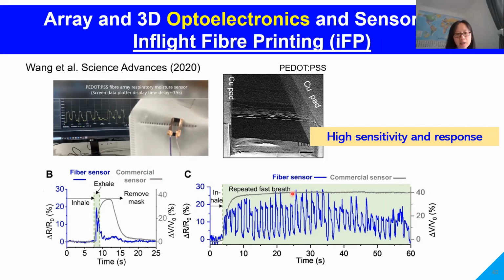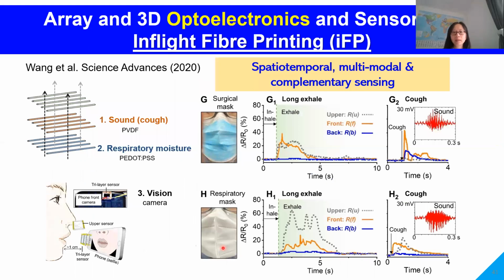And here is an example where Andy, the first author of this paper, is performing rapid breathing in the mask. You can see that our sensor was able to pick up the individual breaths, but not the commercial sensor. Now, by stacking the fibers in layers and having different fiber materials in different layers, multimodal and spatial sensing can be designed. Again, as an example, what we demonstrated in this paper is that we stacked the piezoelectric fiber and the PEDOT-PSS fiber together, and therefore sound information and respiratory moisture information can be collected.